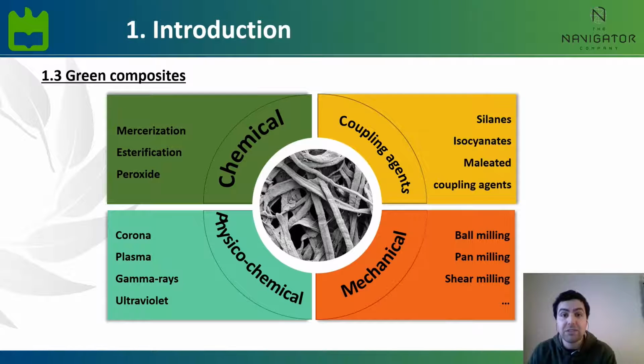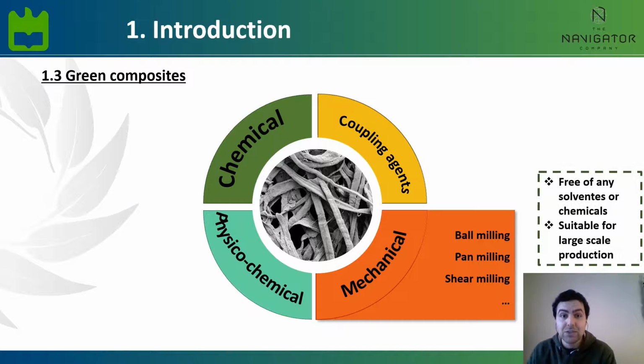And another alternative to avoid fiber agglomeration are the mechanical processes such as ball or pan milling. In there, the goal is to reduce the size of the fibers and improve the dispersion without the use of any solvents or chemicals. And in fact, that, together with the fact that these processes are easily scalable, were the main motivations why we used mechanical treatments for our work.